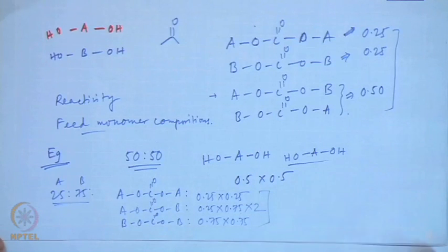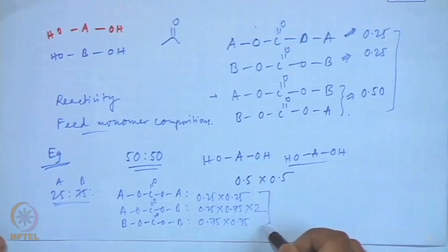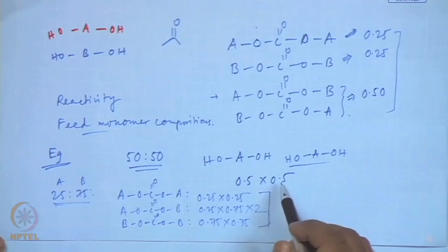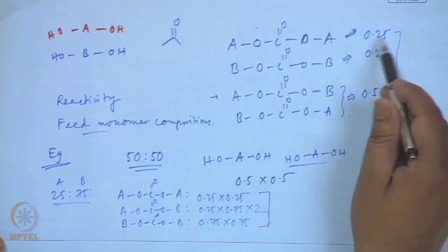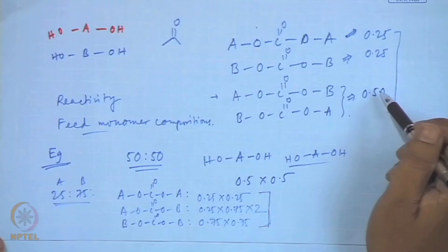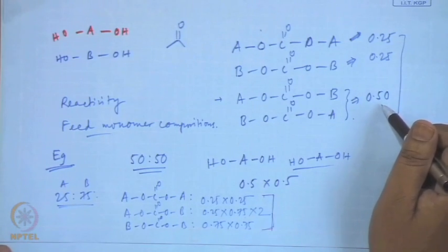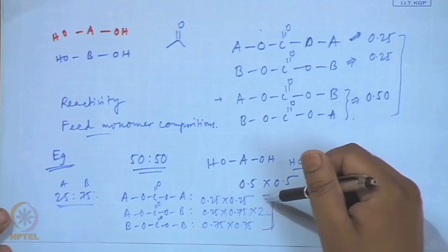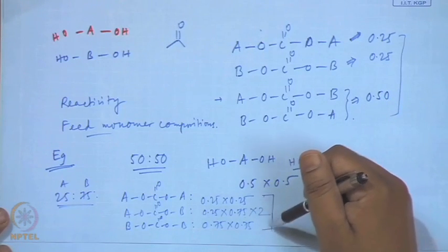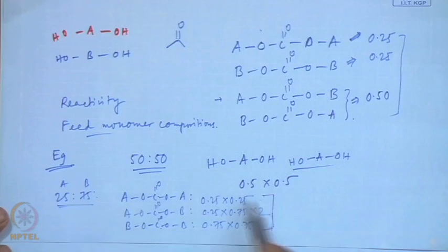If we find, after the polymerization, from our carbon-13 NMR that the ratio of these 3 carbonates for the 50-50 feed ratio matches these values, then we will know that it is a random copolymer, so the reactivities are not different. Similarly, if we have this ratio of these 3 carbonates, then we will know that this is a random arrangement.